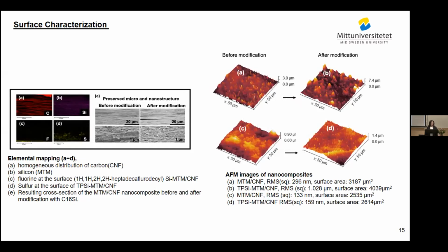We analyzed this surface using the elemental mapping, and here we have carbon that comes from the CNF and silicon from the MTM, and we can see the even distribution here. And this picture C is about the modified MTM-CNF with the fluoroalkane. We can see here the high density of these chemicals on the surface, and this is the one modified with the mercapto. But if we compare this picture with the fluorocarbon, we see that we have some penetration, but actually it is reasonable due to the size of the mercaptosilane compared with the fluoroalkylsilane.